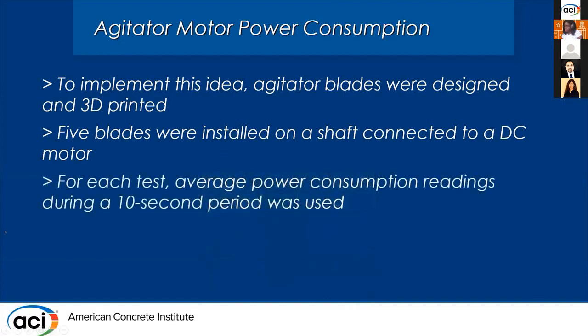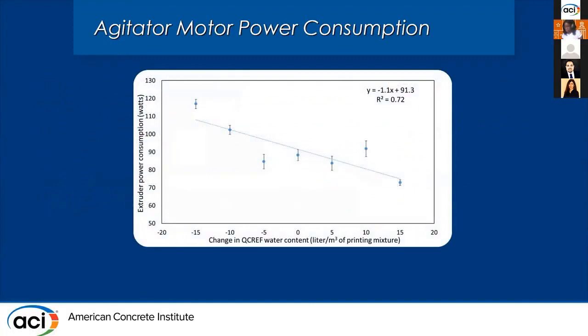And for each test, I used the average of the readings during a 10-second period, and I repeated the experiment for each of those variation levels 4 times, and I used the average as the result of that test for a specific variation level. Here you can see the results. The standard deviation was in the range of 1.6 to 4.4 watts, and as you can see, as a general trend, as the amount of water in the mixture was increased, the power consumption of the motor was going down, which makes sense because the viscosity of the printing material goes down by increasing the water content.